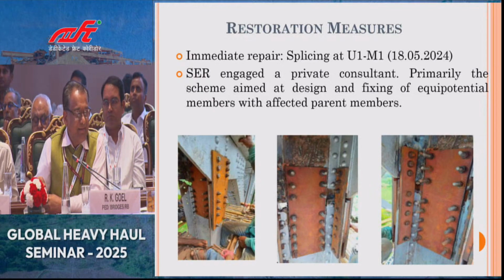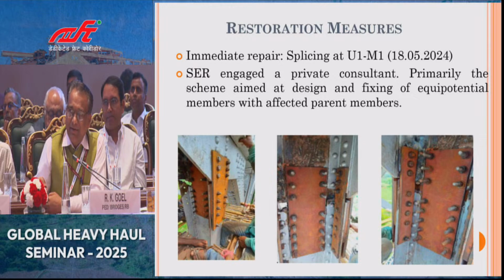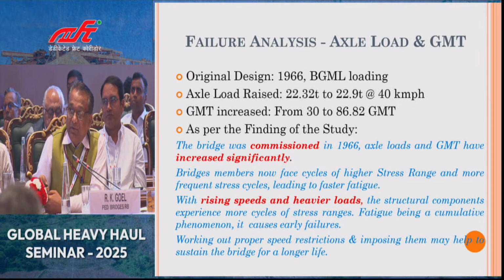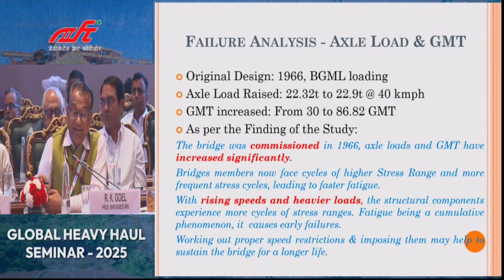Structural Engineering Research Center, the most reliable agency available in this country for doing such kind of instrumentation, and now it is being monitored by them. So when we did the analysis of these failures, we found the girder was commissioned in 1966. The original design, 1966 BGML loading, axle load had been raised from 22.32 tons to 22.9 ton at a speed of 40 kmph, and GMT was increased from 30 to 86.82.